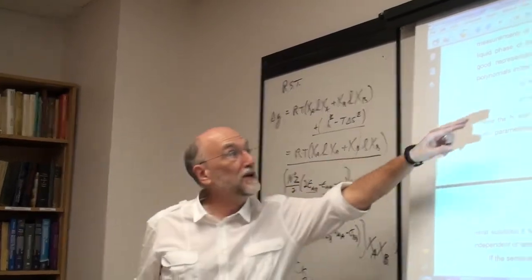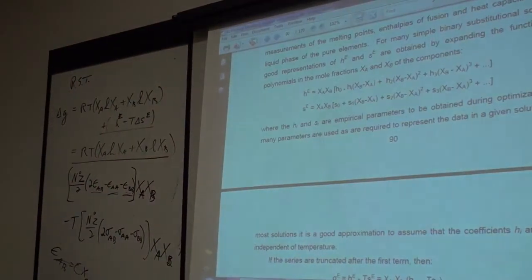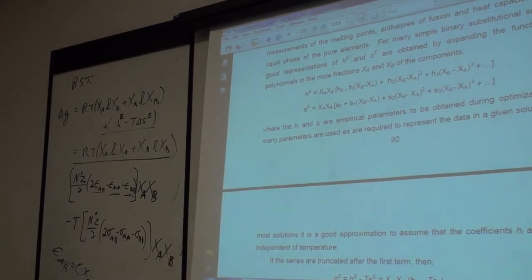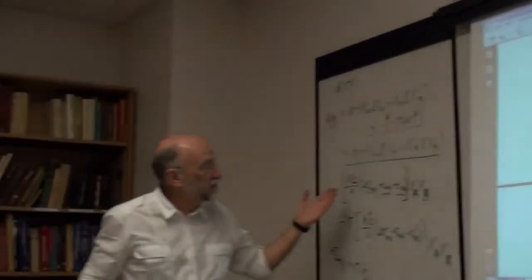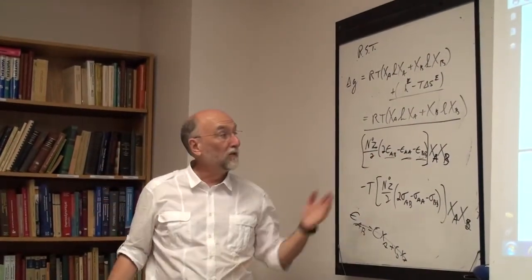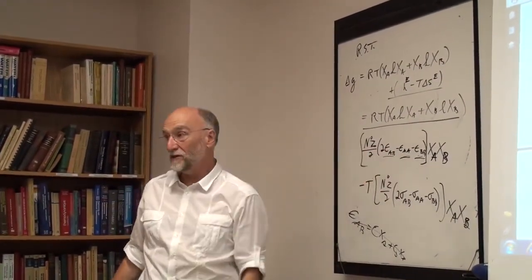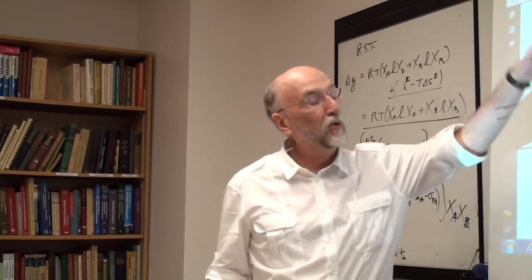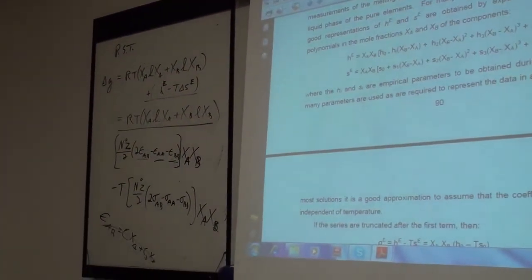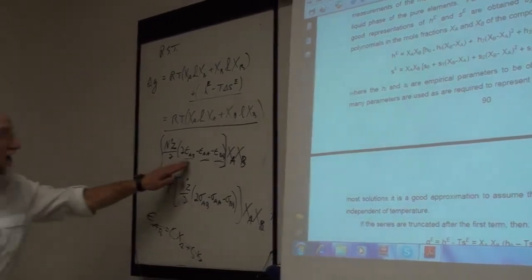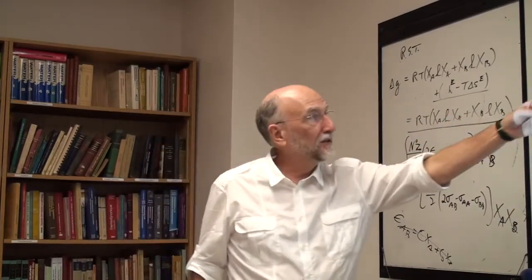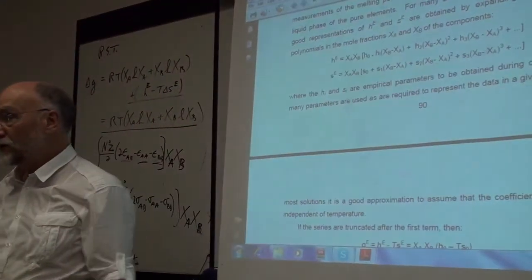And this could be applying to the first or the second or the third nearest neighbor. So to say exactly what H0, H1 are in terms of which bond you're talking about, but you're assuming that some of the bond energies vary linearly with composition, you would get a second term. That seems to be a reasonable assumption. If you wanted to go one step further, they vary quadratically with composition, well then you're going to get a square term. So put it very simply, the variation of the energies, epsilon with composition, will give you a polynomial type equation.